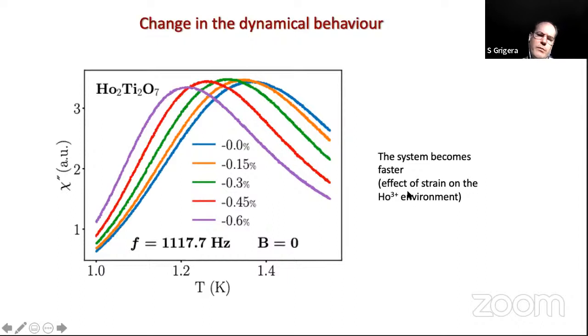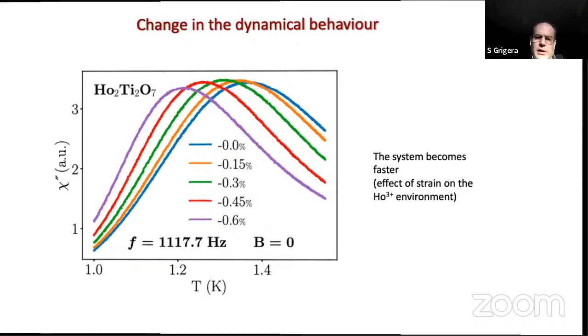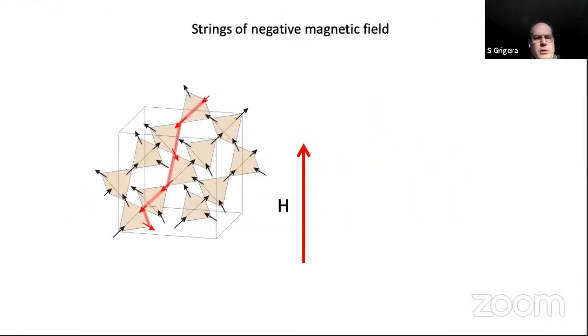One thing that is interesting from putting this uniaxial pressure is what we see here, this is now the imaginary part of the susceptibility as a function of temperature. We see that as you start putting uniaxial tension, there's a big shift in the peak of the imaginary part, which is essentially telling you that the dynamics of the system is changing. This is a quantum effect. This has to do with the fact that you're changing the holmium environment, and now you're making the system, if you want, a little bit more quantum mechanical, and that's why you start seeing a different dynamic.